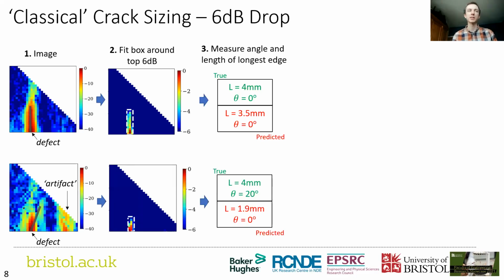So, for example, take this case, where this is a more highly angled defect. The indication of the corner is completely detached from the one of the tip, just because of the way it's angled. It's massively undersized. And this wouldn't be the case if we could transmit more plane waves. We had more information from this defect, but because of the limited data, this is what we've got.